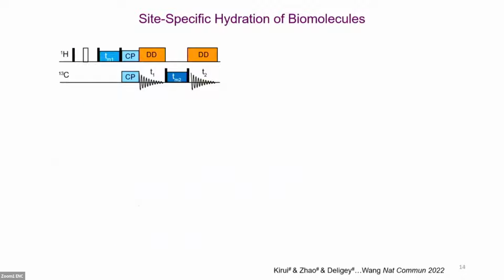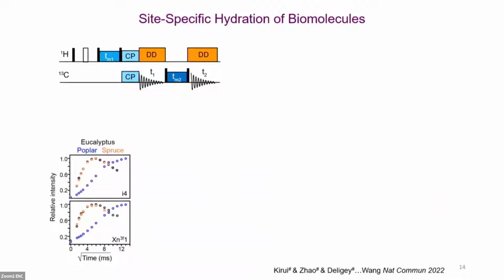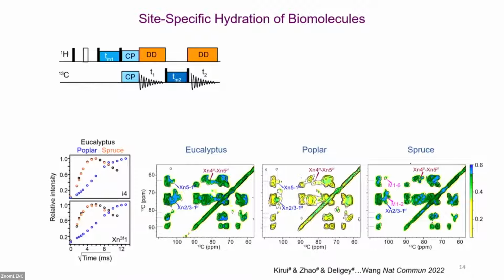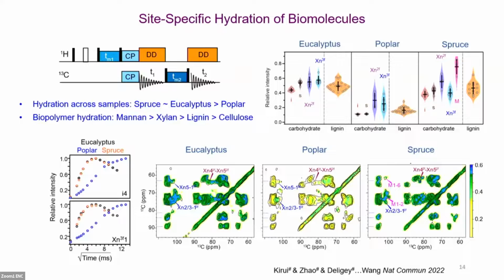Now we want to get the hydration level of the wood samples. We use this water-edited spectrum with a DARR mixing time and get this 1D build-up curve and this 2D water contact map. Both of them show us that poplar is the worst hydrated wood sample. And when compared across the different biopolymers, we can see mannan is the most hydrated one, but cellulose is the hydrophobic one, no matter in which kind of wood.